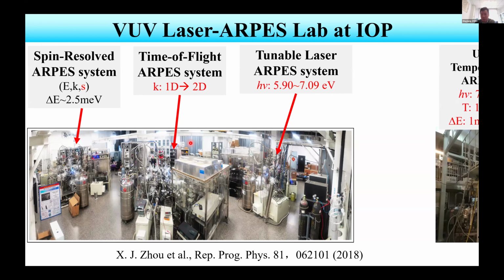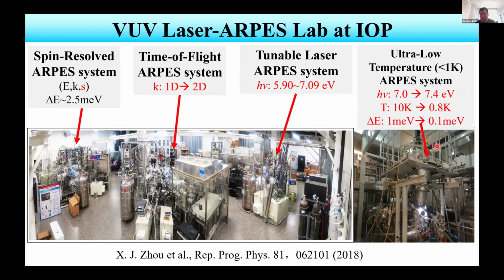And last year, we developed the fourth system, the so-called ultra low temperature ARPES. In this system, we can cool the sample from the usual 10 Kelvin to below 1 Kelvin. We can achieve 0.8 Kelvin at present. I think that's the lowest temperature so far people can achieve in ARPES measurements. We also further improved the energy resolution from the previous 1 meV to better than 1 meV. We can achieve something around 0.4 or 0.5 meV. We are trying to reach 0.1 meV resolution.